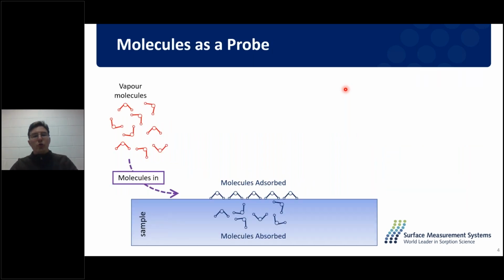So when I introduce my molecules over my surface, they can interact in a number of different ways. So they can interact by just adsorbing onto its surface, and that's what we would call molecular adsorption. When we're looking at this from dynamic vapor sorption, from a sample that would only be going through surface adsorption, we would expect very little uptake, anywhere between 2% to close to 0.1%. That would be as a result of just surface adsorption.